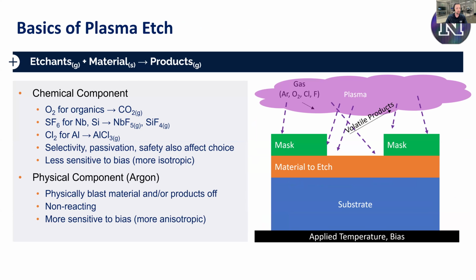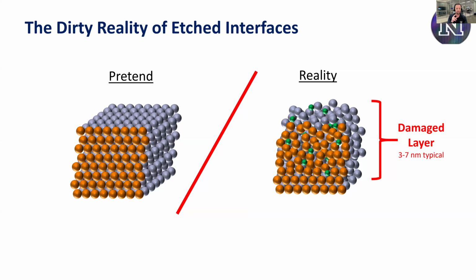So no matter how nice that interface was before we began dumping energy into it, when you start contaminating this thing with chlorine and fluorine and argon, and you're just smashing stuff into it, you are creating a damaged layer that's typically anywhere from 3 to 7 nanometers of the surface. It can be more, it can be less, and that damaged layer will depend on how much energy you're dumping into the interface. Remember, with these quantum devices, incredibly sensitive to loss, to any kind of perturbation. This isn't good. These interfaces look a lot like the big scary boogeyman of the quantum field, which is these two-level systems, these glassy amorphous systems.